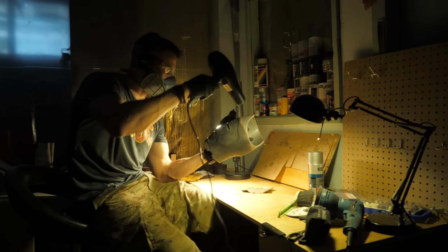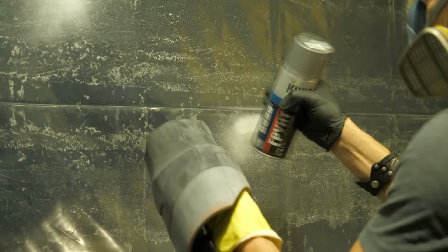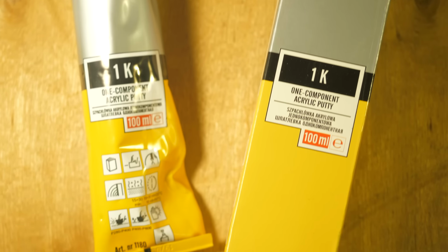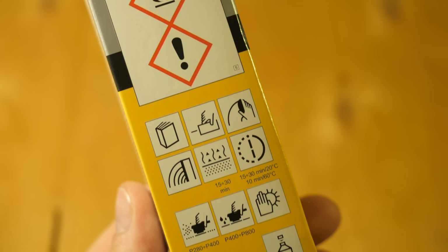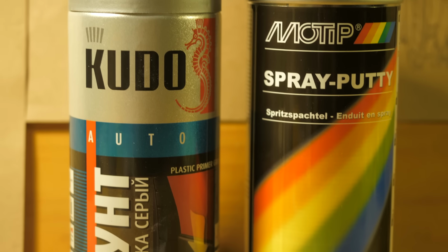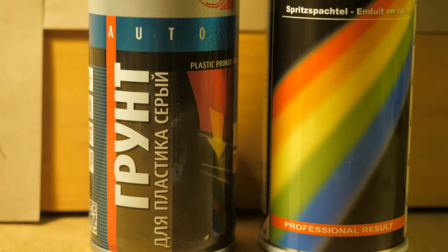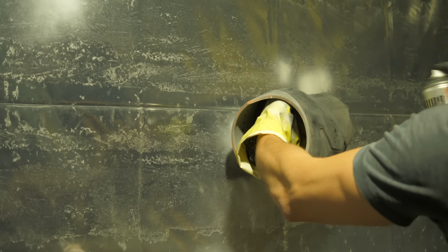Then degrease and prime the part with a spray primer. I just now learned the difference between filler and primer. It turns out that there are two different things. The filler fills in deep defects and holes. The primer smoothes out small imperfections in relief and ensures good adhesion of the detail and paint.